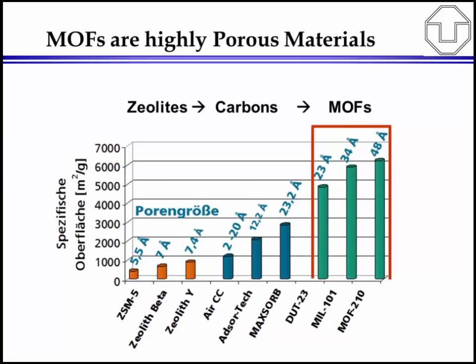This is really why MOFs are exceptional as compared to other porous materials. They are outstanding with respect to specific surface area. They can reach specific surface areas up to 6,000 or even 7,000 square meters per gram. You can see that on the right-hand side. MOF 210 and MIL 101 are the typical names of these record porous materials, with extremely high inner surface area. They are also outstanding as compared to carbons and zeolites, the traditional porous materials, with respect to pore size. Here it is also possible to achieve well-designed pore sizes which are in the nanometer regime, 2, 3, or even 4 nanometer in diameter, and this is what makes metal organic frameworks special. Next slide, please.